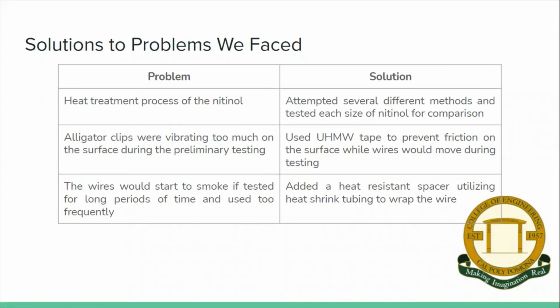For a few solutions to problems we faced, we found that the heat treatment process of the nitinol kept giving us problems. So we attempted several different methods and tested each size of nitinol for comparison until the actuation began working properly, as stated in a previous slide. We noticed the alligator clips were vibrating too much on the surface during the preliminary testing. So we wrapped the end of the clips in UHMW tape to prevent friction on the surface while the wires would move during testing. We also found that the wires would start to smoke if tested for long periods of time and used too frequently. So we added a heat-resistant spacer utilizing heat shrink tubing to wrap the wire.